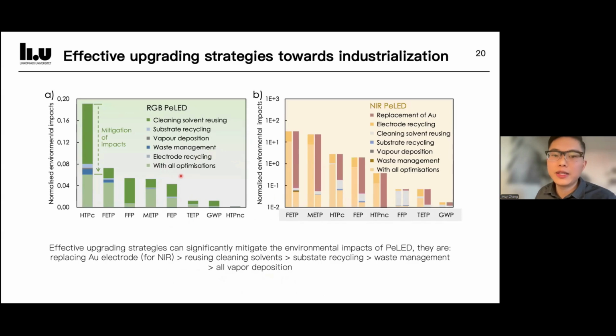So we identified and simulated 6 to 7 technological mitigation strategies. Like for RGBs, we can see that reusing cleaning solvents, recycling substrates, and optimizing vapor deposition can each reduce impact. And when you combine all of them, the impact drops by more than 50%. And for near-infrared perovskite LEDs, which we know suffer from high impact due to gold, the single most effective fix is replacing the gold electrode, which brings down the impact by orders of magnitude. So that's very huge. So in summary, these technical strategies offer a clear and achievable path to greener, industrially scalable PeLEDs. Considering the priority, replacing gold electrode for near-infrared is the most important. Then it's reusing clean solvents, recycling substrates, waste management, and vapor deposition.